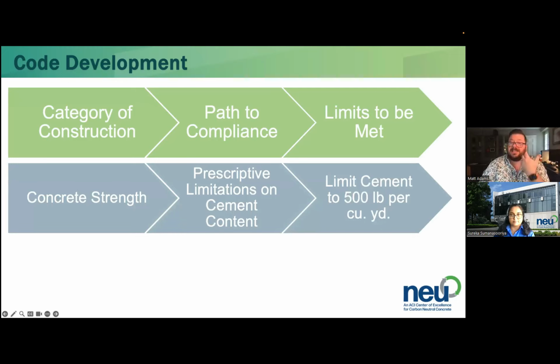When it comes to low carbon concrete, this can look something like breaking the categories into different concrete strength levels, setting prescriptive limits on the cement content, say, that can be a path to compliance. So you can only use a certain amount of cement in your mixture. And then that limit is, say, 500 pounds per cubic yard. So this is a path that has been used. This is essentially what Marin County has implemented. We know that this is not necessarily the best path because concrete strength is not necessarily related to GWP. You don't always get a higher global warming potential when you have a higher strength concrete. And so it's not always the best path to go down, though right now, in terms of data, that's really where we have a lot of data.